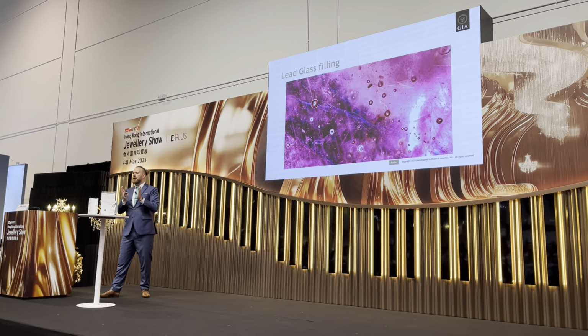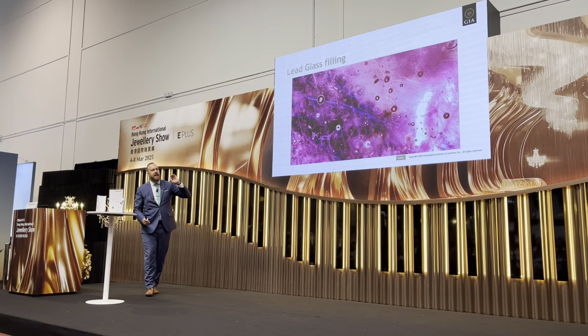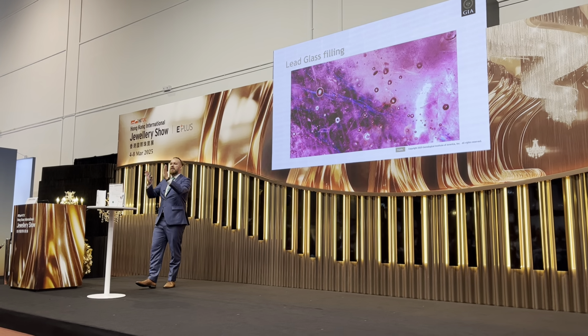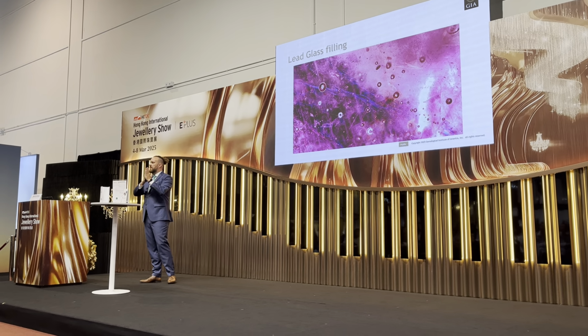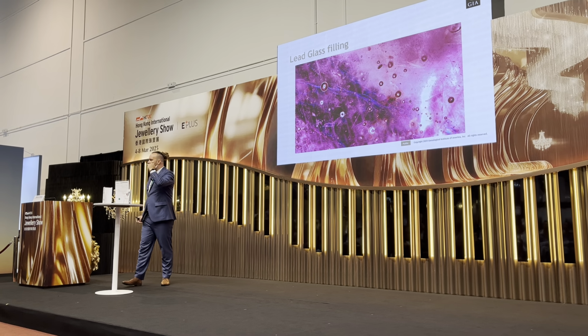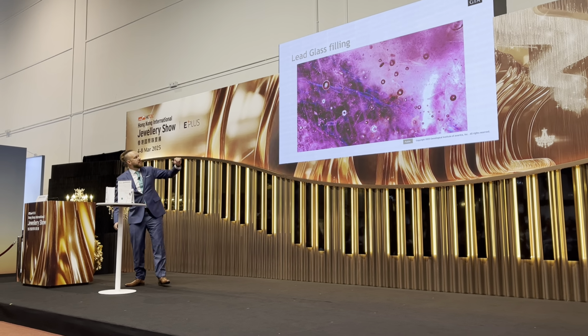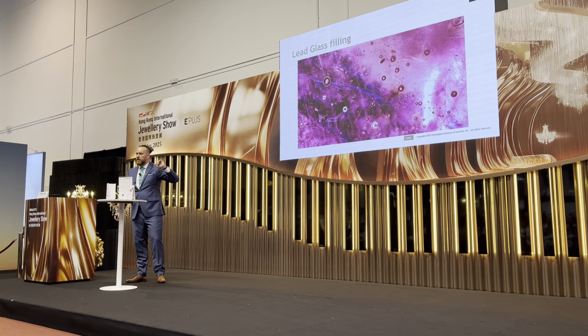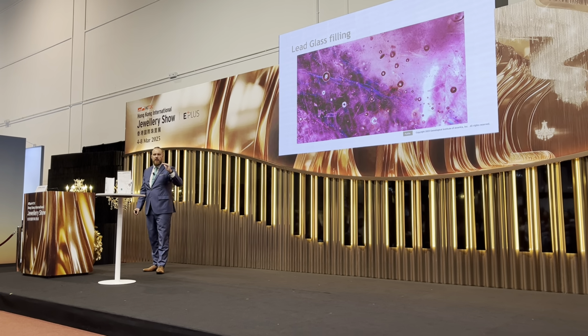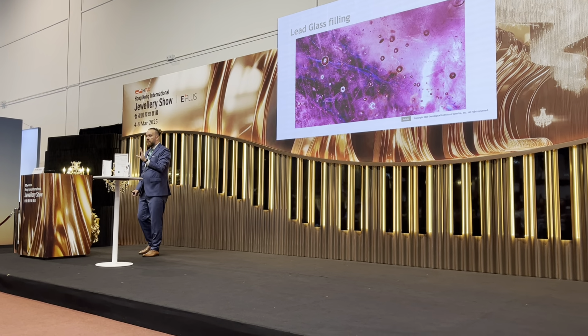And how do we know they're not 100% the same? Because where they touch, where the corundum and the lead glass touch on the side of the fracture, we see these slightly colored flashes. So we see these blue lines running through it. Sometimes they're green, sometimes they're yellow. And these can be very obvious.